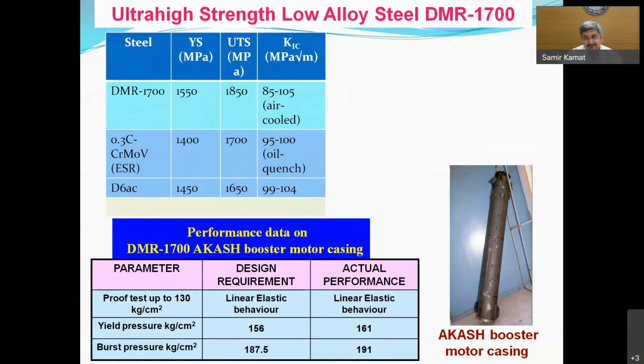But DMRL explored whether this steel could be used for other applications. And since DMRL was also looking at armor applications for our Arjun Mark 1A program, DMRL was able to use this steel in much higher plate thicknesses, of course, 50 mm and 80 mm, which was made at SR Steel. And DMRL was able to use the same steel for armor application. And it has helped in reducing the weight of the Arjun armor by about 10% and will now go into the Arjun Mark 1A, which has been ordered by the Army recently.